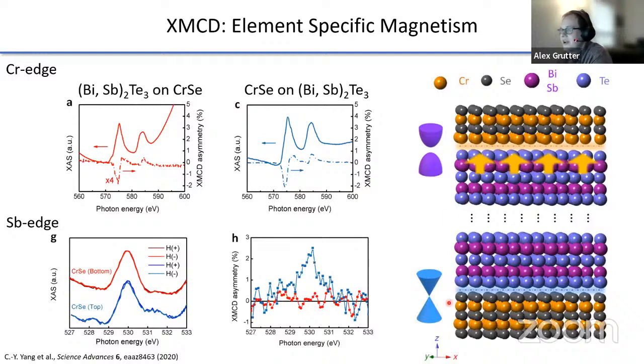On the other hand, if you grow chromium selenide on the bottom, it ends up being tellurium terminated at the interface. And then you get basically no strong magnetic interactions across the interface and no magnetic proximity effect. So having combined neutron reflectometry, transport data, electron microscopy, and element-specific information from X-rays, this is, I think, the ideal approach of throwing everything in the kitchen sink at one system and trying to really understand what's happening.